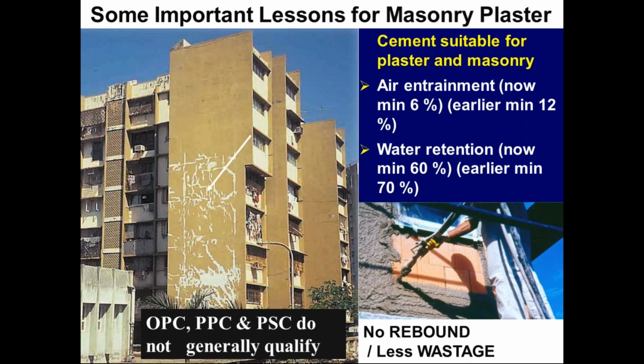Now, there are two important properties like air entrainment. Even with our normal mortar which we make, you can improve the air entrainment by adding an air entraining admixture and then measure it so that you can fix the quantity of air entrainment so that it gives at least 6% air entrainment as per the present standard. Again, water retention, you can improve. There are various options. There are chemicals available to improve the water retention. And there are minerals like fly ash and slag, which you can use.